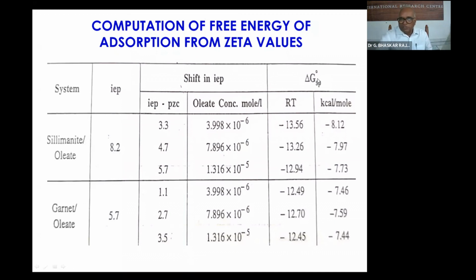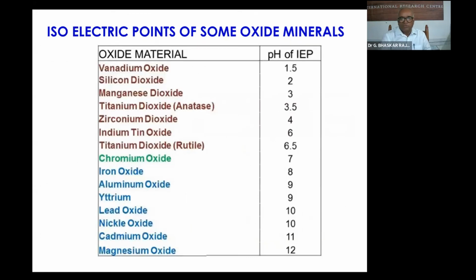Otherwise, for this type of values, even if it is not a physisorption, you can say a weak interaction between sillimanite and the oleic acid. So by calculating these delta G values, we can predict what type of interaction is taking place, whether it is a specific interaction or a weak interaction between the substrates.